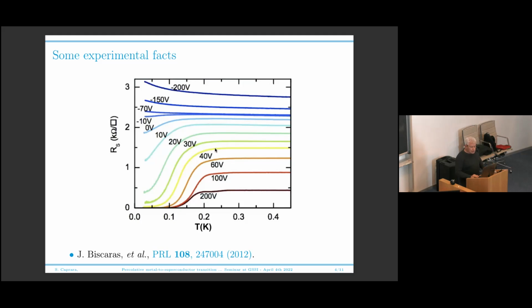Now you reduce the charge density, you reduce the gating. So when you go up with these curves, you are reducing the carrier density in your system. And of course, the resistance in the metallic state increases. The system is less and less metallic until in the end it becomes insulating-like. This is a weakly localizing insulator. And your superconducting transition temperature decreases. You see that you go from this situation to this, to this, to this, to this, and this. What was striking, this was 10 years ago.